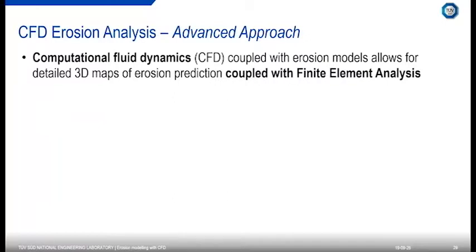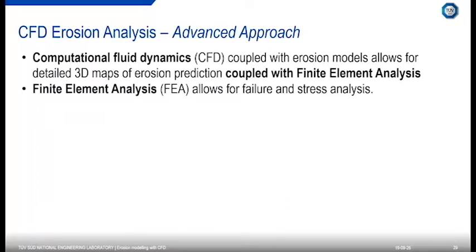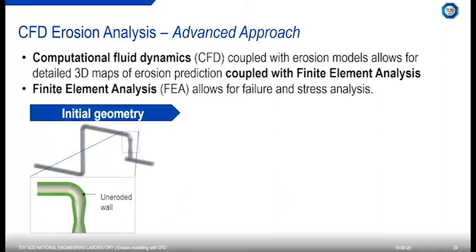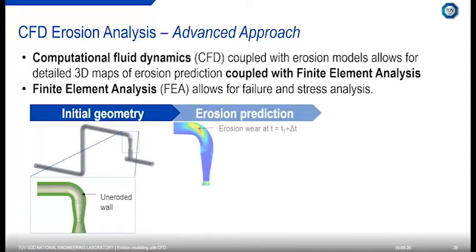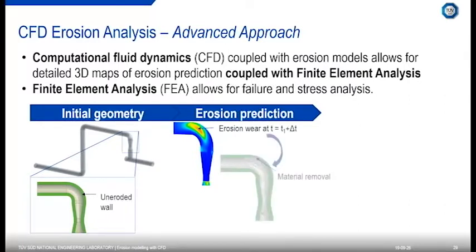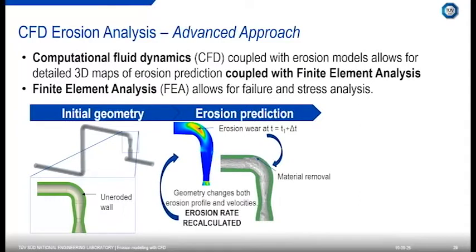So this actually allows us to provide a 3D detailed map of erosion. And we can take a step further as well, and we can couple it with finite element analysis. And this allows us to look at failure and stress. So just another example, if we have an initial geometry, we've got a pipe with an uneroded wall. In this example, the wall is incredibly thick. We then have our erosion prediction. Most of this happens at the bend. The material gets removed. We then recalculate the geometry.